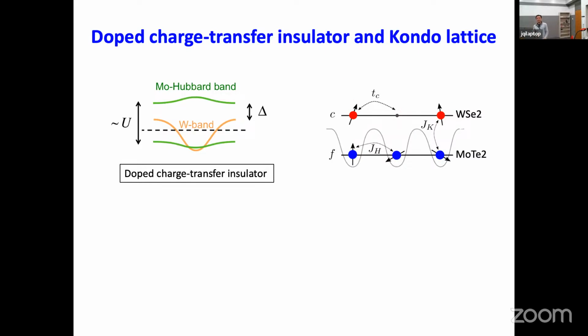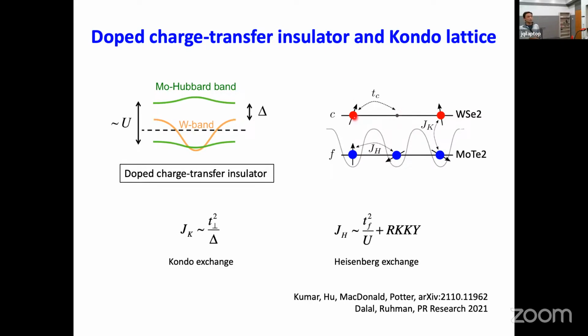And the two types of carrier can exchange couple through the Kondo exchange, which one can also estimate using the out-of-plane tunneling constant T perpendicular divided by the charge gap of the system. So actually the Kondo exchange is also totally tunable. It's of an Anderson type of super exchange for this Kondo exchange mechanism. And in addition, the presence of free carriers in the tungsten layer would also produce an additional RKKY exchange between the local moments in the system, in addition to the Anderson exchange. Okay, so effectively, you realize a Kondo lattice model by just doping a charge transfer insulator.